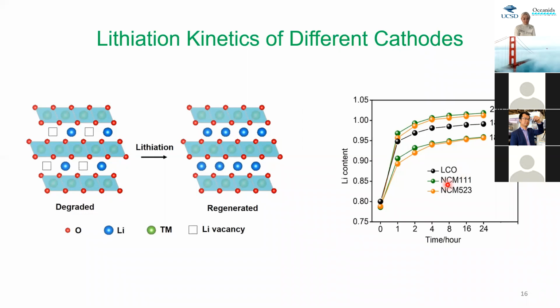And for NCM, N is nickel, C is cobalt, M is manganese. Talking about 111, that is the nickel, cobalt, manganese ratio in the mole ratio 1 to 1 to 1. And by saying 523, that means their ratio changes to 5 to 2 to 3.